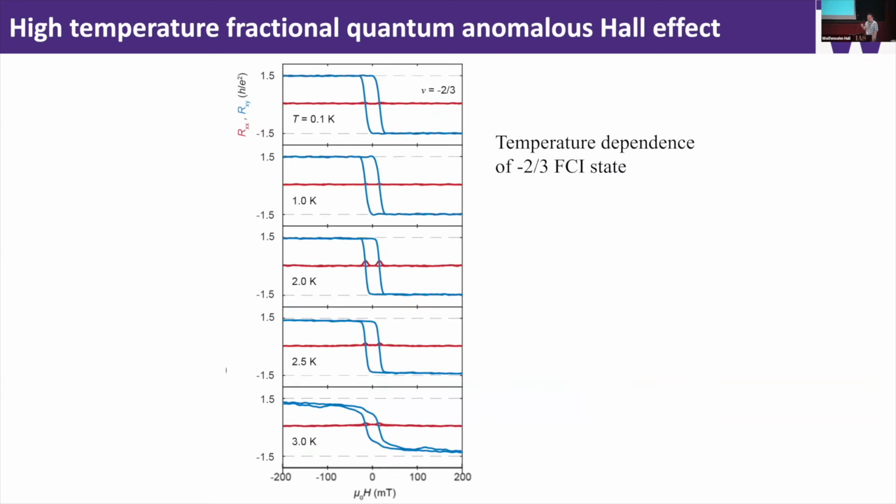One of the important features of the system is that the energy gap of these FCI states is really large. What I show here is the measurement of Rxx and Rxy as a function of temperature, from the top at 100 millikelvin all the way to the bottom at 3 kelvin. What I would like to emphasize is that even at 2 kelvin, you'll see Rxy is still nearly quantized and Rxx is suppressed. So this really suggests that the system has a very large energy gap. This is the data from the -2/3 filling. I didn't show you the data, but for the quantum anomalous Hall state at the integer filling, it's nearly quantized up to 6 to 8 kelvin, so it's a very high energy scale.